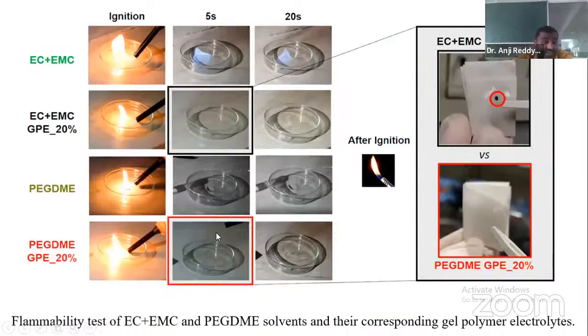Right? And they did a flammability test also. This is one of the important tests nowadays. They tested the EC-EMC gel polymer electrolyte and the PEG-DME gel polymer electrolyte, these two particularly. Okay, this is after firing, after the flame retardant test. See, after firing, how is this looking? See, one black spot. Not that much fire retardant, but PEG-DME, we are saying this is a highly safe plasticizer. See, that is very good after the flammability test also. But this EC-EMC is not that good after the firing test. That means whatever polymer electrolyte they synthesized here is safe and one of the good materials.